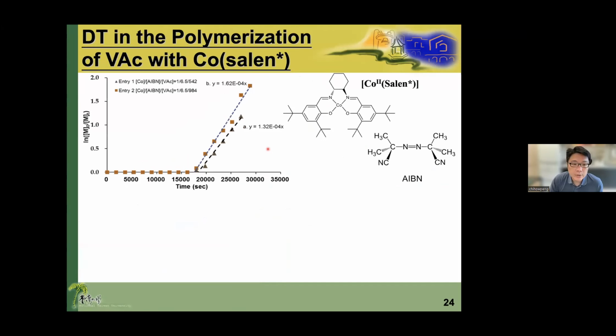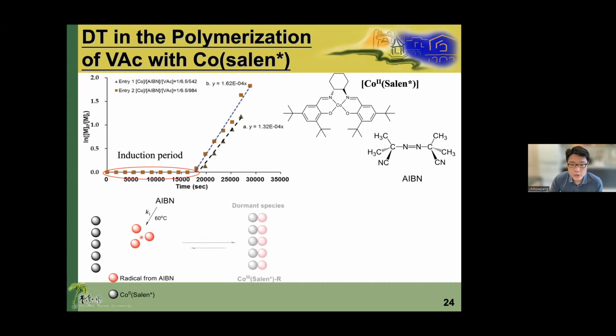And the behavior of cobalt-mediated radical polymerization can be shown by this figure. So you can see, according to the kinetic plot, a period of induction, and then the polymerization starts. This is because, according to our study, we understand when AIBN injects the radical into the solution, the radical is all trapped by cobalt(II) and converted to organocobalt(III) species, so that during this period, because all the radical was trapped, no polymerization can be observed, and you observe only the induction period.